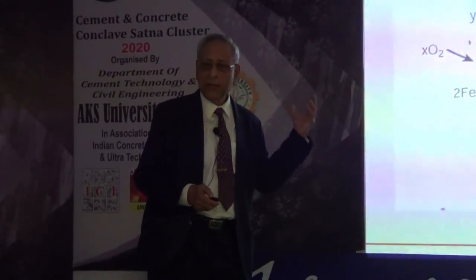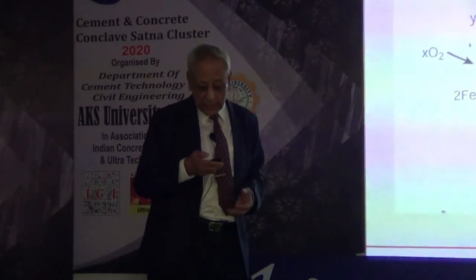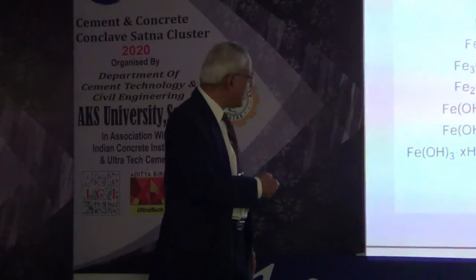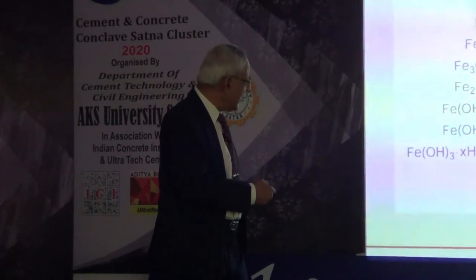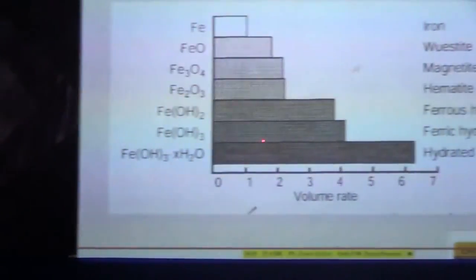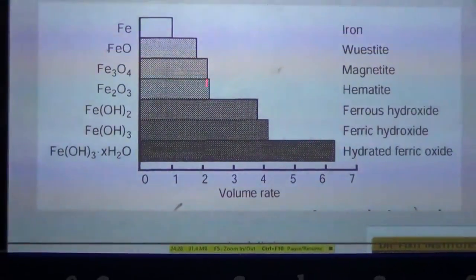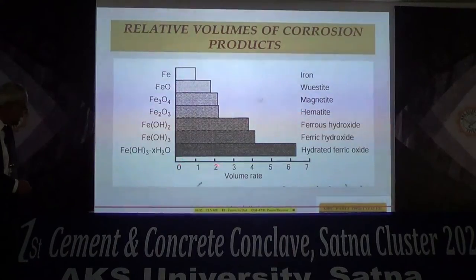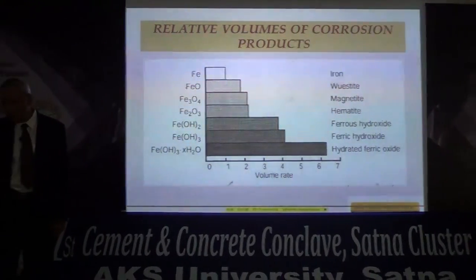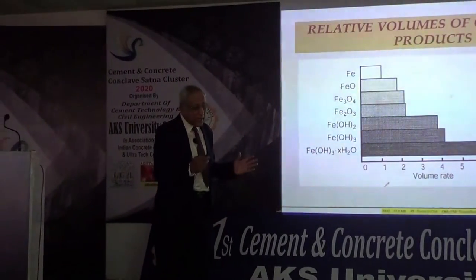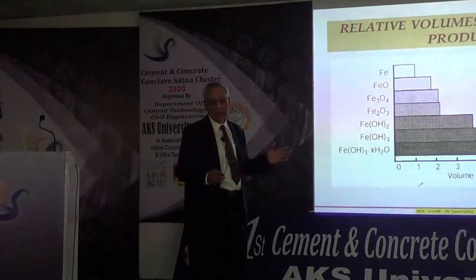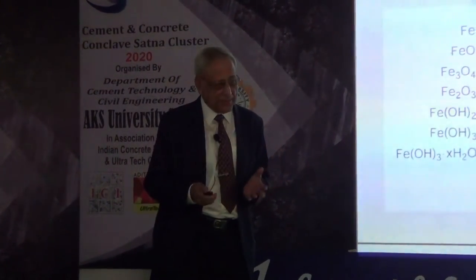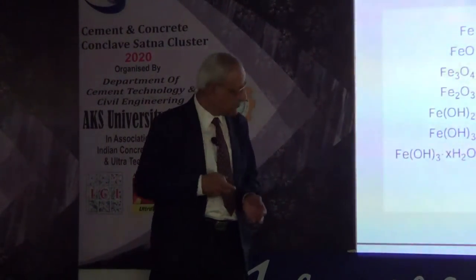And this is one of the fundamental problems of concrete, which creates a hell of a problem for all of us. And then the interesting part is that if you look at iron and keep seeing the different oxides and hydroxides forming in the system, then your volume increase can be anywhere up to 7 times, mind you. And with that kind of a volume increase, what happens? The concrete cannot withhold its expansion and cracking propensity, and concrete spalls off.